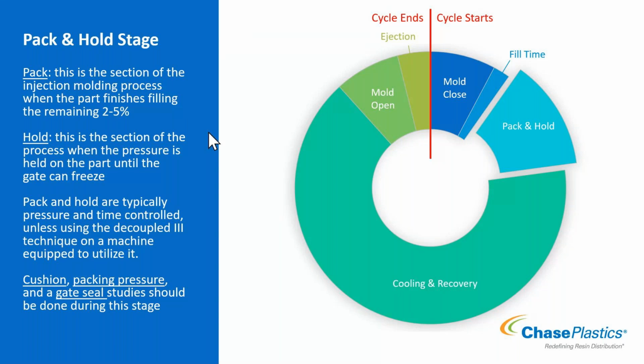Now, because we're still putting volume into the cavity in pack, we still have a velocity component to that piece of the puzzle. Pressure is the control variable, but the screw is still moving forward. Many new molding machines will give you control of that velocity for your pack. What differentiates pack from hold is hold drops its velocity component. Once we've generated a set pressure in packing, because we're still driving that screw forward to generate that pressure, as soon as we hit the desired pressure, we can stop the velocity component and hold the screw static at a given pressure.